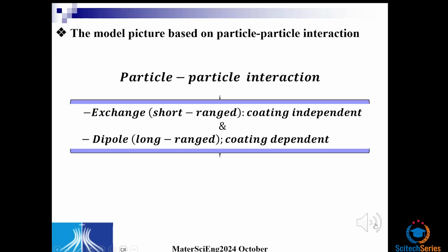contributions. The exchange contribution, which is typically a short-range particle-particle interaction, and therefore should be coating independent. And the second contribution is the magnetic dipole-dipole interaction, which is typically a long-range interaction, and that depends on the coating thickness, exactly the way we see the data. We saw that the saturation magnetization systematically reduces as the number of carbons in the chain of the surface coating species increases. And that is due to the dipole-dipole interaction, which is typically the long-range interaction.